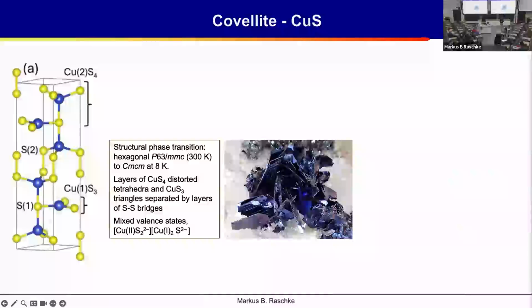Now, there's a mineral you can find in Colorado which shows the same behavior. This was actually discovered much earlier. And this is covellite. Covellite is a copper ore. It forms nice iridescent crystals. And you would think this can't be a very complicated lattice structure if you just have one copper and one sulfur atom per unit cell. But it actually turns out, and this is again a theme you've seen a few times, we have two sublattices where these copper ions sit in a different coordination. So we have this tetrahedral coordination, and then we have a planar coordination, and they alternate. And so we have two sublattices, and this makes us suspect that something interesting can happen.